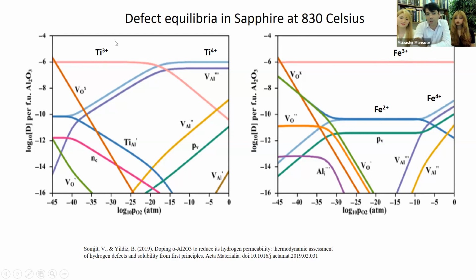Same here. If you actually are playing with oxygen partial pressure, you can change the valency of titanium based on oxygen partial pressure and temperature, of course. But these diagrams are very interesting, but unfortunately, the professor's group at MIT only did this for one simple condition, and this isn't enough for us to understand the heat treatment process. But this is so crucial.